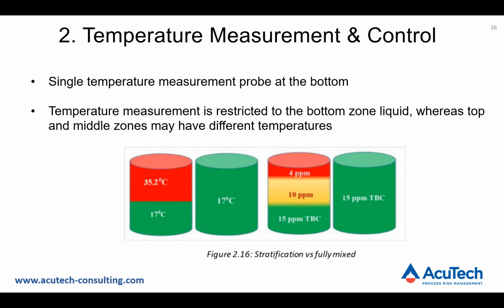There should have been at least 4 to 5 temperature measurements along the 12-meter height of this tank to measure the true temperature of the different zones in the tank. The tank M5 had temperature measurement probes at 3 locations, but M6 had only at the bottom. And the operations staff always believed the bottom temperature to be the temperature of the whole bulk of the liquid, which was incorrect, and that led to the thermal stratification.